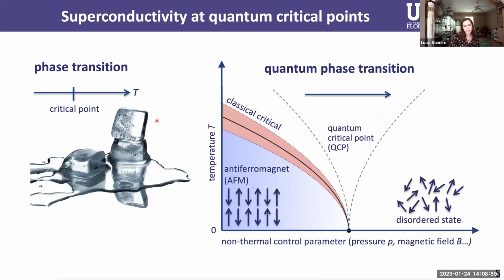But temperature is not the only thing that can drive a phase transition. There can also be other control parameters, such as pressure or magnetic field. Those are called non-thermal control parameters, and in combination with temperature, they allow us to draw a phase diagram. Now, the example that I'm considering here is a magnetic material that orders antiferromagnetically, so with anti-parallel moments below a critical temperature. If my control parameter allows me to continuously suppress that phase transition until it happens at absolute 0, this is when I've reached a quantum critical point. Now, there's a lot of fun stuff happening at quantum critical points like this. And one thing that you may find there is an unconventional superconducting phase.